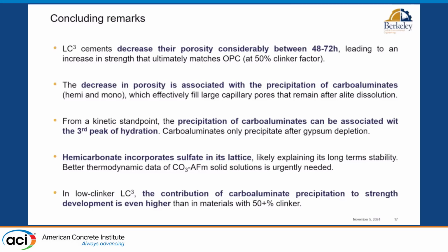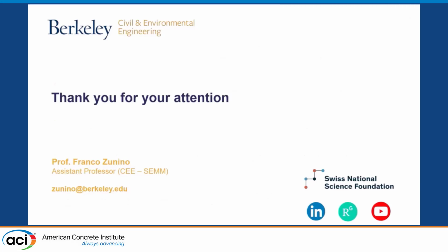And in low clinker LC3, what I mean, 50% is already low clinker, that's much better than what we have in the market now. But with low here, I mean less than 50% clinker, the contribution of carboaluminate precipitation to strength development is even higher than at classical 50% clinker cements. So with that, I would like to conclude.